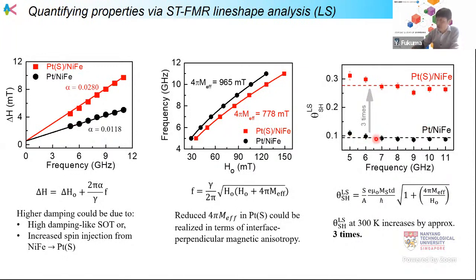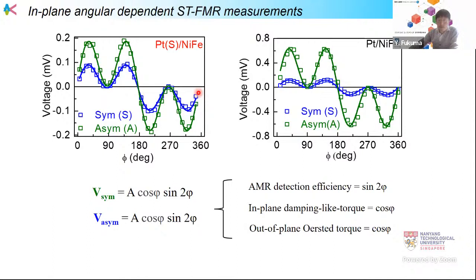Then it's almost independent behavior as a function of the microwave frequency. We also check the spectra as a function of the in-plane angle. What we can see here is that both the symmetric and antisymmetric components show cosine phi and sine phi behavior. Actually, we can say this behavior is expected from the detection efficiency, and also from the torque. From this fitting, we can conclude that all the torque components here are as expected from the measurement setup. I explained it in the previous slide.